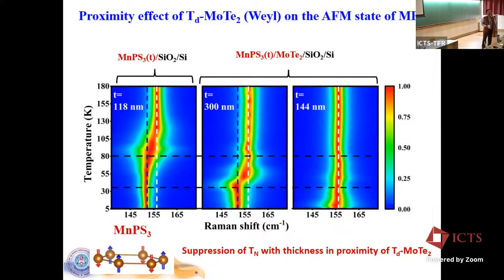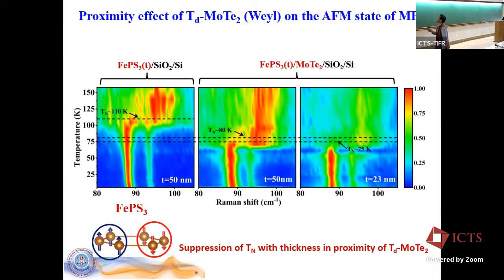Then we looked at the other 2D systems, the FePS3 and NiPS3. Let's look at it. So this is FePS3 on just the silicon substrate, no change in the magnetic ordering temperature. Here with MoTe2 underneath, now you see that 110 or 115K has gone down to about 80K for about 50 nanometer thick FePS3. And if we go to about 20 nanometers, it has gone further down to about 70-75. So there is a lowering of the Néel temperature even for FePS3.